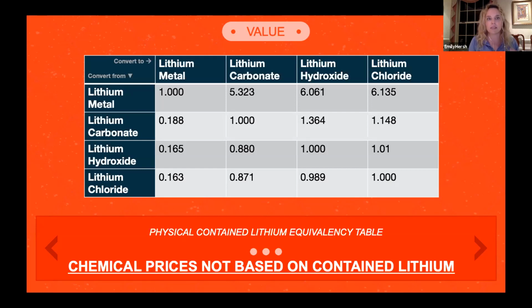And that's because the chemical combination of the lithium in the hydroxide allows the reaction to make a cathode to occur at the lower temperature that a high nickel cathode requires. So the price of a lithium compound is not like gold or copper, where you take the weight of the commodity multiplied by some kind of purity formula and you get a price. Lithium chemicals are priced by what kind of chemicals the market needs for a certain process, which is changing as battery chemistries change, and also by the purity of not just the contained lithium, but on a molecular level, the other characteristics and what other impurities the lithium chemical contains. And you can see this pretty clearly in the slide I'm about to show you.